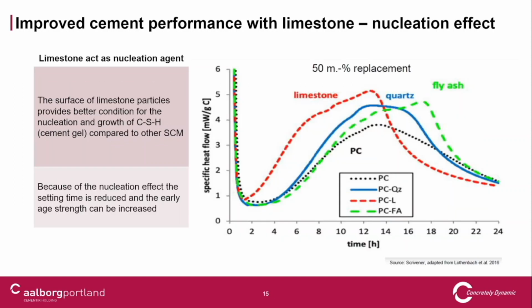The nucleation effect is seen on this graph — similar to what we saw yesterday in the laboratory with the calorimeter, measuring how much energy is liberated within the first 24 hours after mixing with water. This isn't our own data, but it shows replacing 50% of the cement with either limestone, quartz, or fly ash. What happens to the reaction? The neat Portland cement has heat or energy release starting at 4 hours, and then the black curve shows the release of energy representing the reaction of the cement.